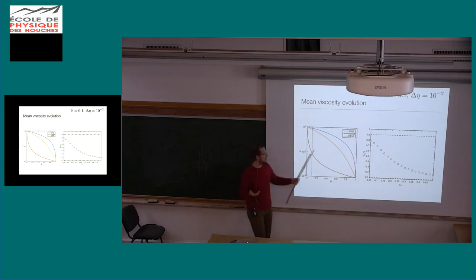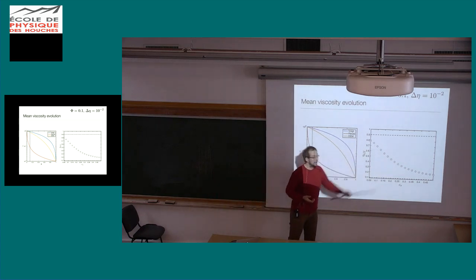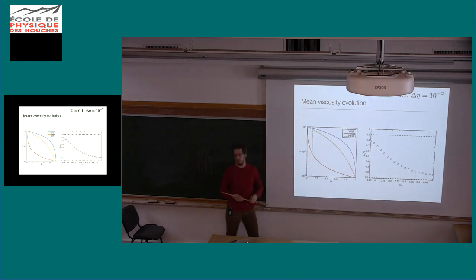So you have this decrease in effective viscosity of the whole sample with more elongation. In the end, I could, in theory, just take this, fit a curve through it, and then put it in my model. But the problem with this is that it's for a very specific setup. And that means if I would like to have a parameterization for the mantle, I would have to run loads of those models until I get a proper description of all the possible cases. So in the end, what I want is some kind of analytical, semi-analytical solution that describes the whole thing better.